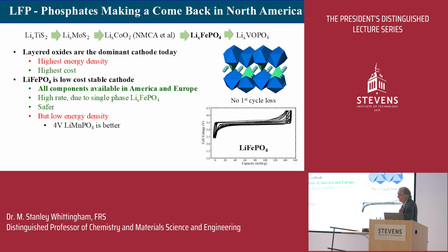Then we went to the olivine, this lithium iron phosphate, and that's the structure I showed you here. You'll notice this is the three-dimensional structure, no longer layers. So it's much more stable. It does not evolve oxygen. Doesn't lose any capacity as you cycle it, but too low energy density. So we're working on these, what we call vanadium phosphates. For the chemists here, they all know vanadium goes from vanadium 5 to vanadium 3, so you can put 2 lithiums in. The others, you can do one oxidation state. So this is a low-cost, stable cathode.